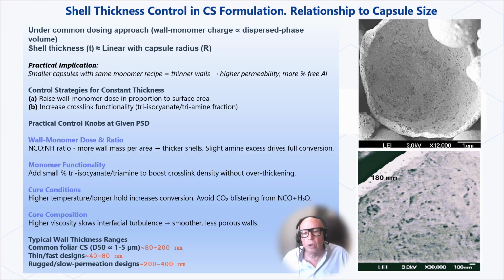Shell thickness control in CS formulation. Relationship to capsule size. Shell thickness control is trickier than many realize. Here's the key relationship. Under typical dosing approaches, shell thickness scales linearly with capsule radius. Smaller capsules with the same monomer recipe give you thinner walls, higher permeability, and more free AI. It's a geometric reality we have to work with.